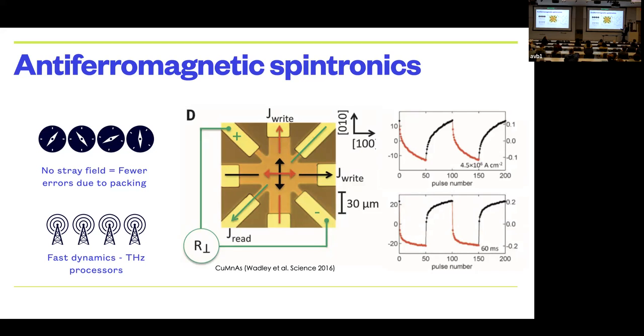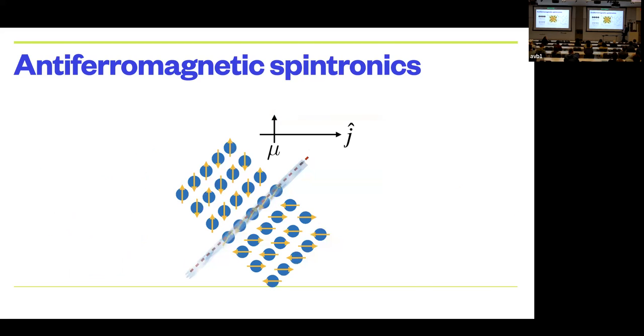Well, it's to do with the mechanism of how this works. How do you go from a low resistance state to a high resistance state? And it's all to do with domain wall boundary motion. So what they're doing when they're applying the current is moving a domain wall boundary, and because of the difference in resistance of this domain versus this domain, you go from a low resistance to a high resistance. So all of that physics of these antiferromagnetic components is really about domain wall motion. And I read about this. I wasn't interested in this kind of thing.